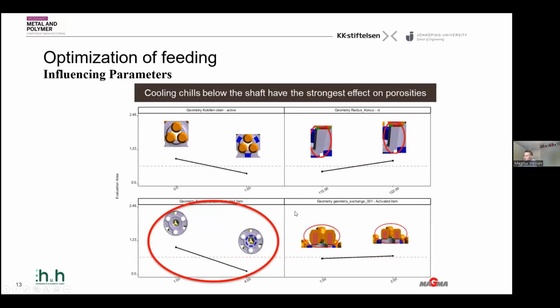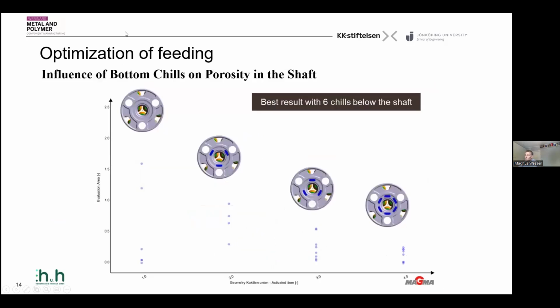So in this case, it's quite simple to set up the variation. You have this variation in this radius or this shaft, different configurations of your chills, and also different feeder sizes. And then the output is quite simple. You can see they have defined some evaluation area, which means they check the porosity in some location, and seen that the best results were obtained with the highest impact from the chills. And easily you can find out that when you have this kind of chill configuration, whatever the other parameters are varying, they're still in a very low and safe range. This is one quite simple case to find out which are the most important factors, and then to design your part to get a robust production.